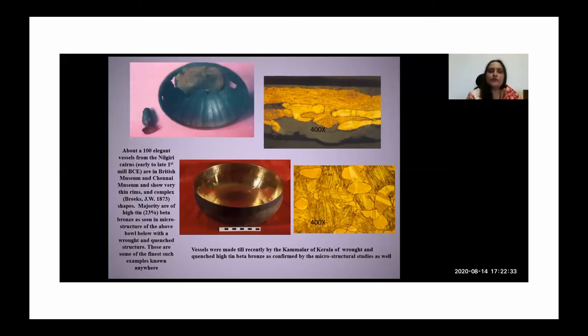Quite a few of these are actually these high-tin beta bronzes. Again, they are extremely finely forged, wrought to a very fine thinness, as you can see from that microstructure with very long elongated needles of beta phase and the alpha plus beta islands, with the annealing twins. This ability to forge this beta phase alloy, 23% tin bronze, is also because of the formation of an intermetallic compound, which is very plastic. It's highly plastic at high temperatures. In fact, it's what is called quasi-superplastic. That was a study done with the late Oleg Sherby. And so that's why it could take this extraordinary degree of forging.